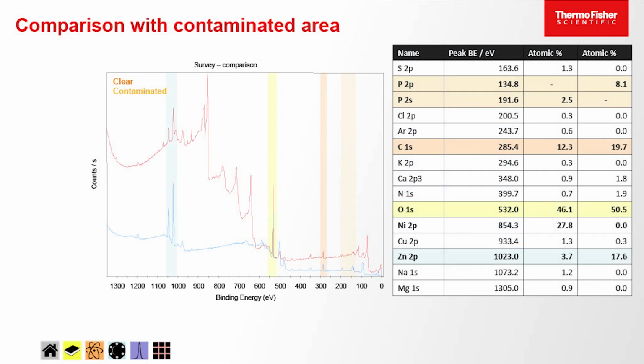Okay, so we just measure the area of the peaks, and the software converts those into atomic concentration. So we can see differences between the clear and the contaminated area. If we look at the oxygen, we can see there's about a 4% difference between, and I've lost the top of the thing to tell me which one's which. So let's see. Yeah, the contaminated area is the one with the zinc, I think. So this is contamination, this is the clear area, and we can see where the contamination is.